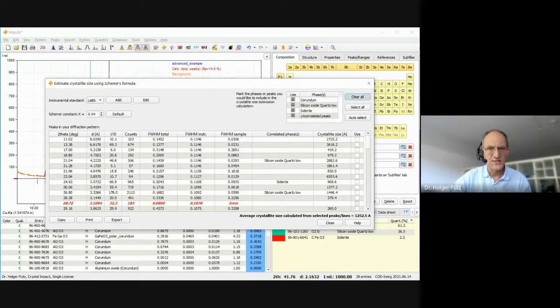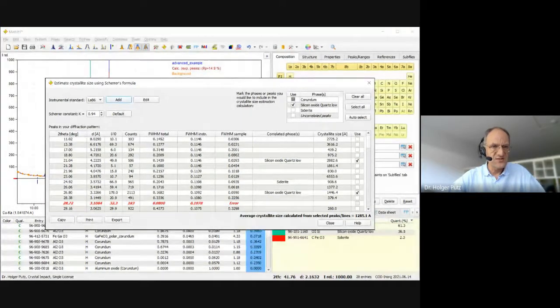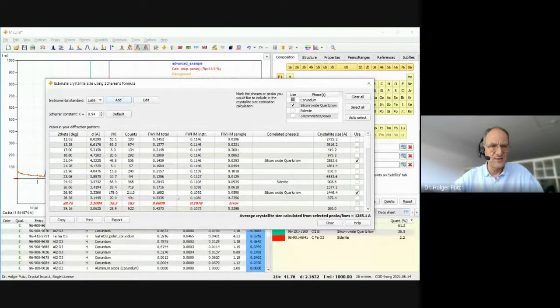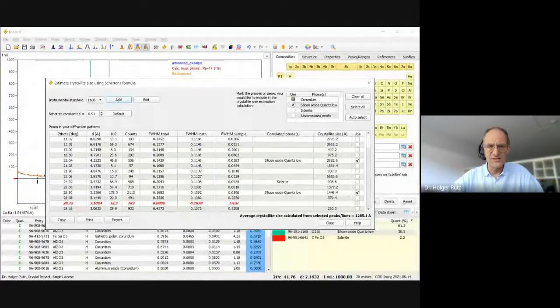What you can also do is select a single phase for the calculation, that is, use only peaks that are present or have been assigned to this phase, in this case quartz, in order to get an estimation about the size of this quartz crystallite in the sample. And finally, there's something special here. You have a line marked in red. In this case, the instrument peak width is larger than the total width measured in your diffraction pattern of the sample. So this is certainly an error, and you should avoid using this information.